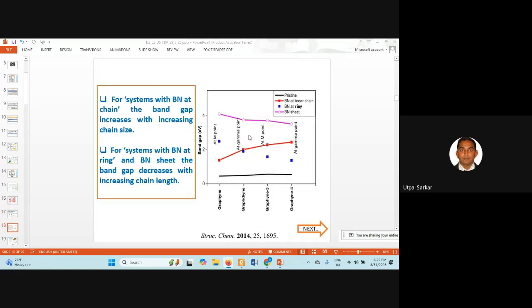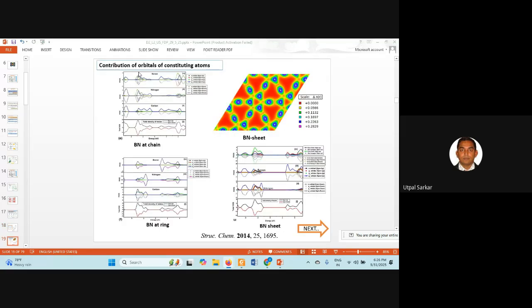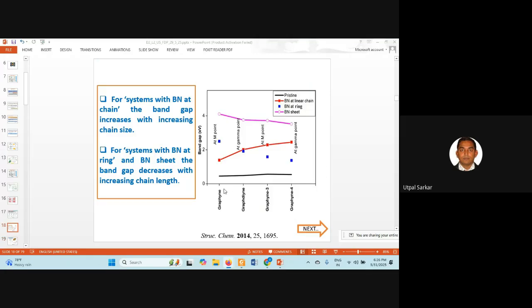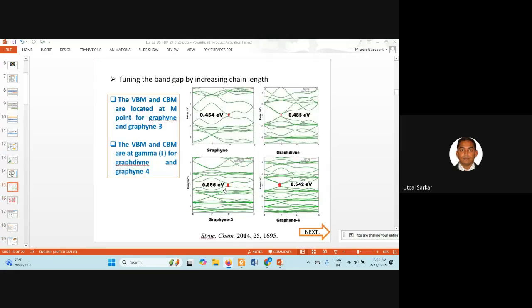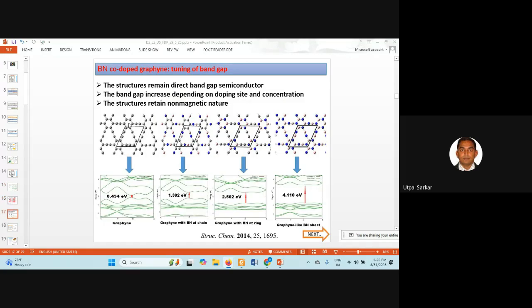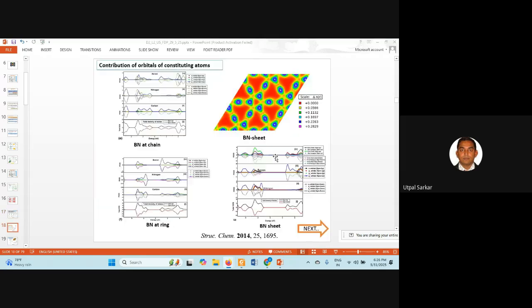So this is the graphical plot of what we have already discussed. Now these are the contributing orbitals for each of these carbon, nitrogen, boron, showing how each is contributing near the Fermi level. So this is the carbon's contribution, this is nitrogen's contribution, this is boron's contribution. You see here that these are basically symmetric, which means it is basically non-magnetic in nature.